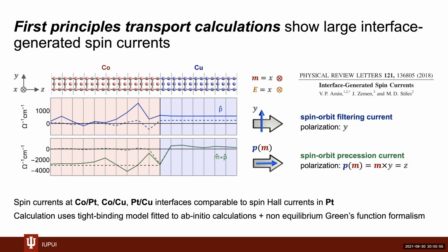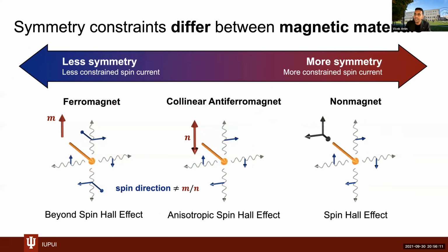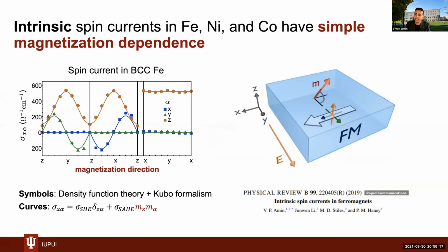I was just wondering about this spin anomalous Hall effect and spin planar Hall effect. These are bulk effects, right? This is the bulk of the ferromagnet, if I understood correctly. Yeah, that's right. So these are effects that occur deep within the ferromagnetic material, and actually they cannot exert torques, again by symmetry arguments, even if the spin direction is not aligned with magnetization in the bulk. They can only exert torques when they flow to the interface of the layer boundaries where inversion symmetry is broken. But yeah, what I'm describing is a bulk effect.